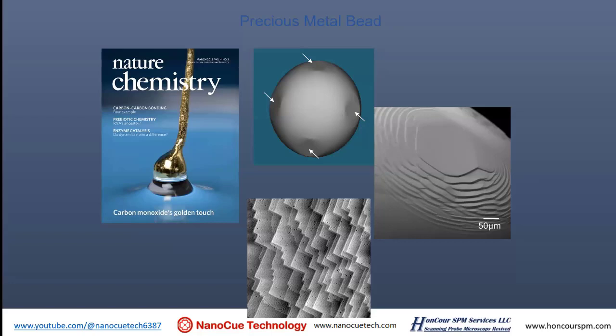If you look carefully at those beads, they're actually not spheres. They're spheres with facets on it. And using an optical microscope, you can actually see those facets. Those facets are flat. The facets are actually the gold 111 crystal orientation surface. And that surface is actually quite flat. And then if you prepare it the correct way, it's quite clean. So that's a good way to do that.